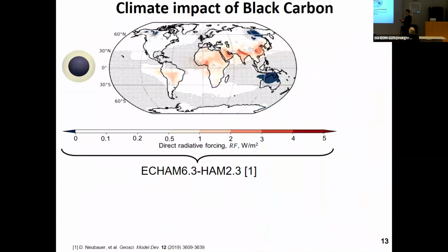So we collaborated with Professor Ulrike Lohmann's group at ETH Zurich, and we used their global climate model, ECHAM-HAM, to get the distribution of radiative forcing across the globe. So here is the model's predictions without any change, just by using the default model of coated spheres. The dotted areas that you see show statistically not significant changes of the radiative forcing of the climate in these regions because of black carbon. In the United States, you can see that we have positive contribution of black carbon based on a radiative forcing of about 0.1 to 0.2 watts per square meter.